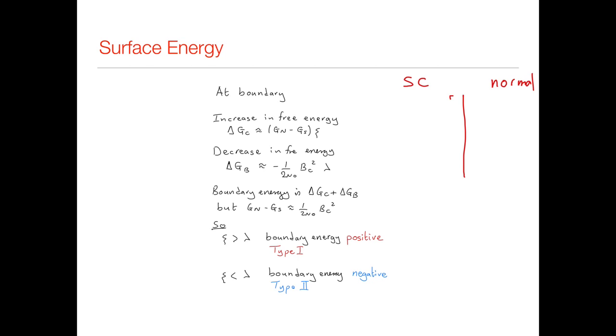Well, first of all, if we look at, for example, the B field, that would do something like this. It would penetrate into the material. So this is a 0, and this region here is lambda. By doing that, the larger lambda is, we get a decrease in the free energy. We calculated this factor before. So the larger that lambda is, the larger the decrease in the free energy.